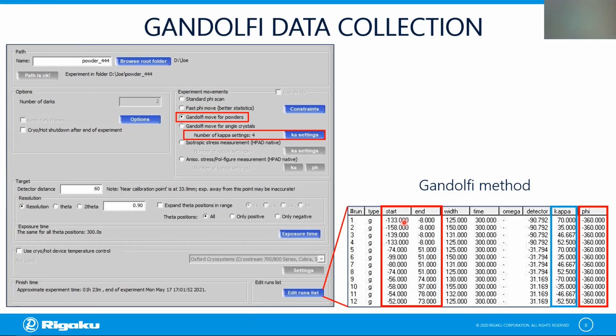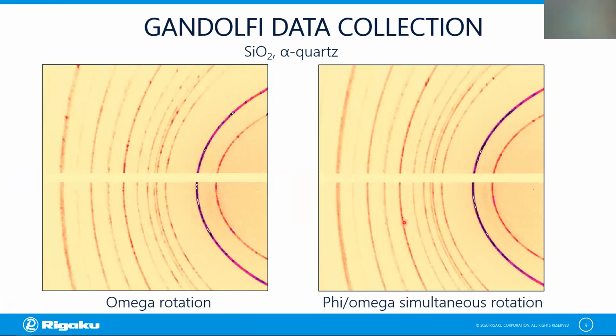So rotating 2 axes instead of 1, here is how it translates onto a diffraction image. On the left-hand side, this is a diffraction image from silica that was obtained by rotating the sample along omega only. And on the right-hand side, I rotated both phi and omega. With the omega-only rotation, you see that the intensity distribution along the rings is obviously pretty uneven, with parts of the rings being more intense than others. On the right-hand side now, with phi and omega rotating at the same time, the intensity distribution along the rings is much more even, if not perfect, but at least it's more even.